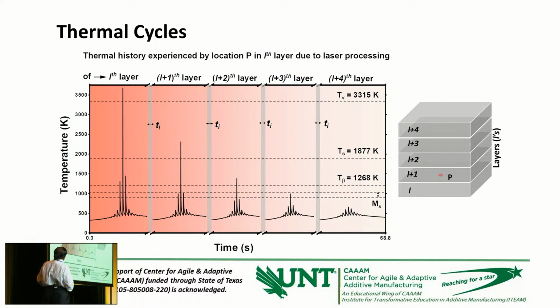And then if I put the next layer up to here, probably this layer here may not have any effect on this temperature. So now it will be stabilized, and whatever forms through these thermal cycles due to layers 1, 2, 3, 4 will be the one which causes the phase transformation and liquid to solid state transformation at this point. After this layer, there may not be high enough temperatures seen by this point.